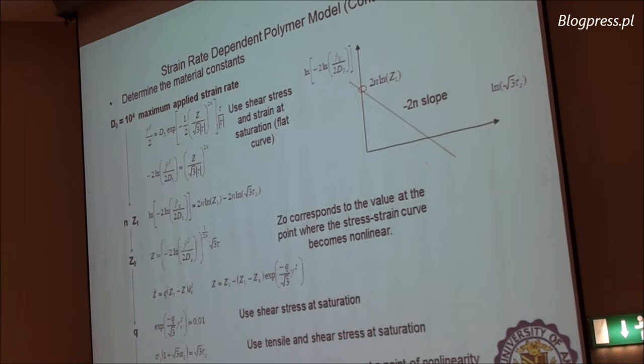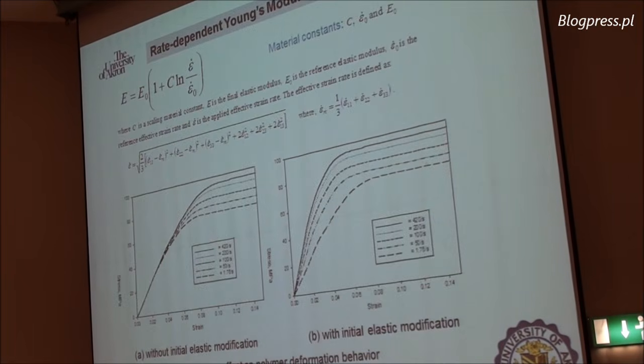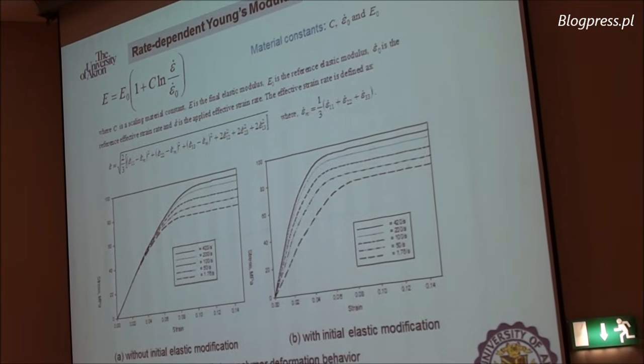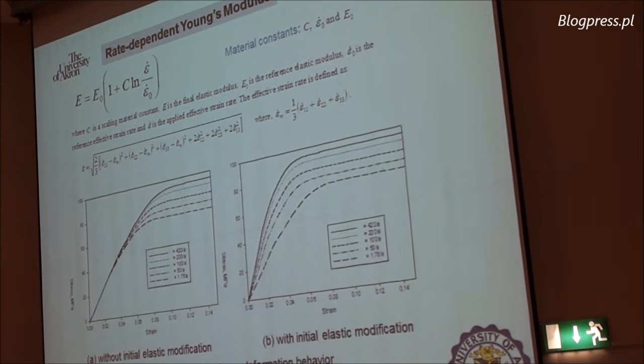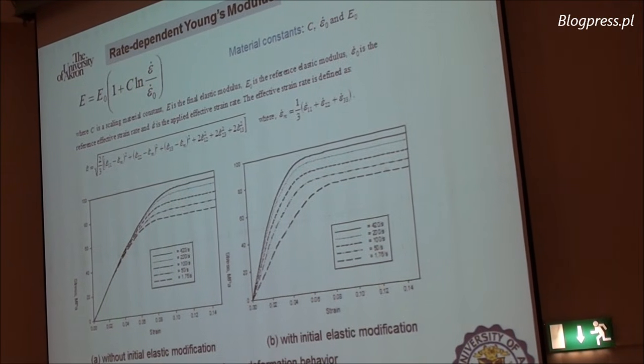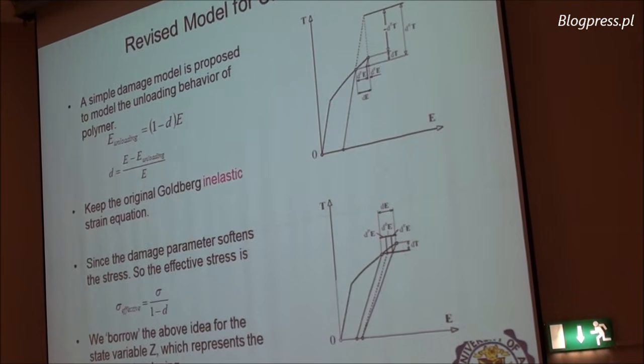And of course this is not finished. We also had to add some damage that is involved in the material itself as a matrix. So the damage is reducing the Young's modulus. You can see that the more the damage, the different slope, even at the beginning of the stress strain curve is obtained, and that needs to be related mathematically, and it was captured using the damage parameter, which is basically defined using Kachanov type of definition.